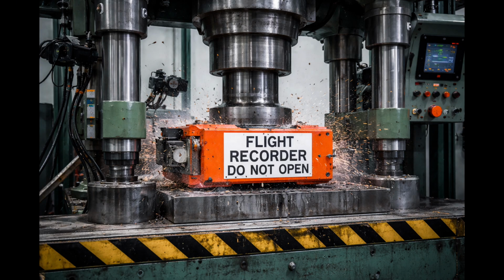Recovered recorders often showed partial charring, warped housings, and insulation layers that had performed exactly as designed, until they did not. Heat transfer is unforgiving. Once insulation saturates, temperature rises exponentially. Engineers learned that delaying heat was not enough. It had to be delayed long enough.